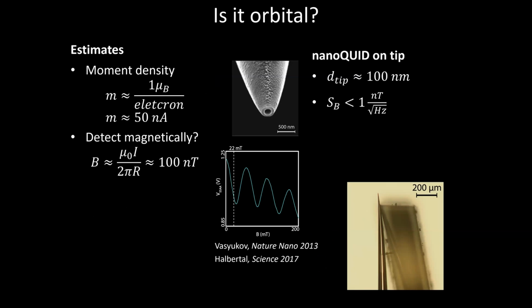Okay, so to do that, I'll just talk about this very briefly. If you ask what the magnetization densities are, these are very low density systems. They have roughly one Bohr magneton per electron, maybe a few times that because of the orbital magnetization. And 10 to the 12, or 10 to the 11 electrons per square centimeter. It's actually one electron per 10 nanometers, or 15 nanometers. It's a very small magnetization density if you want to compare that to an iron magnet, a neodymium magnet that's on your refrigerator. So you can try to say, well, what would it take to actually image this directly?